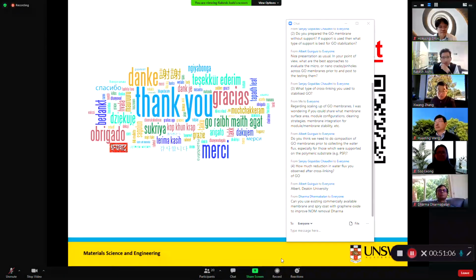How much reduction in water flux is observed after cross-linking? No reduction of water flux. This is for stability without compromising the porosity. So water flux only depends on the porosity, or on the hydrophilic behavior of graphene oxide, which needs functional groups to attract water molecules and make this laminated structure. Cross-linking will not have much effect on water flux, depending on the concentration of the cross-linker we use.